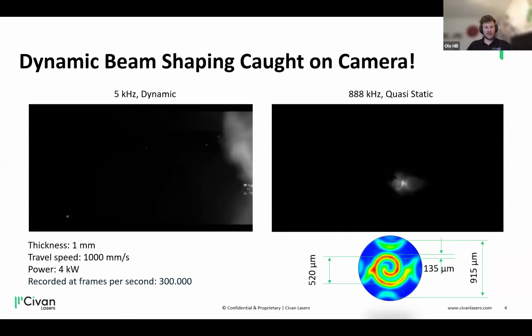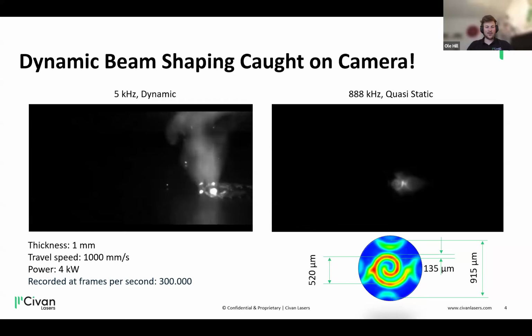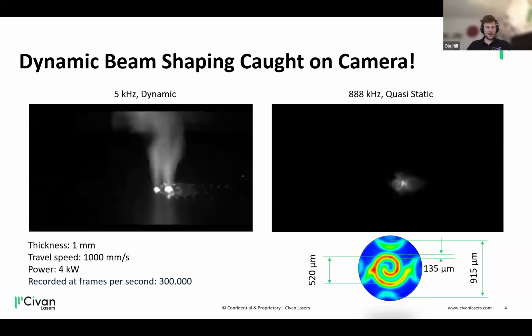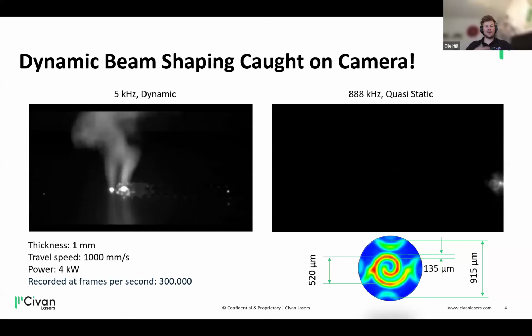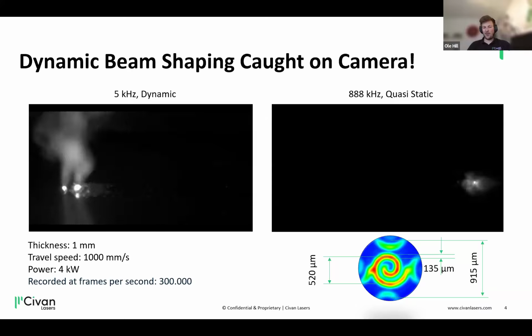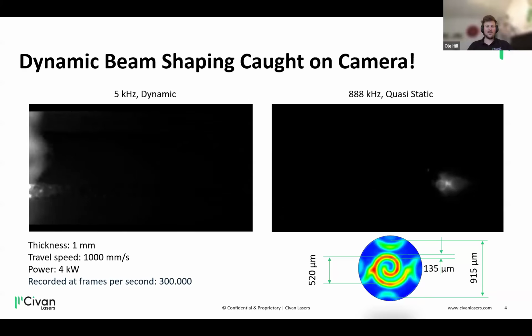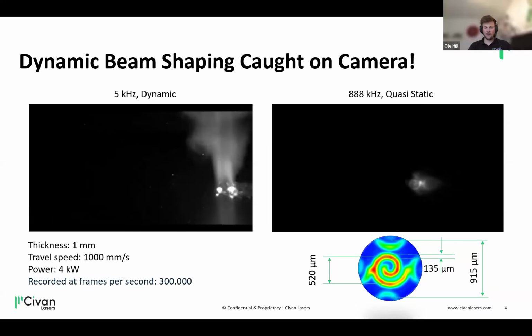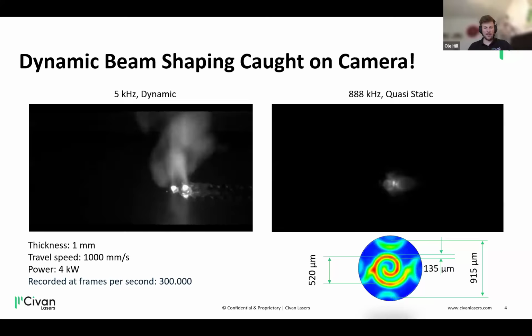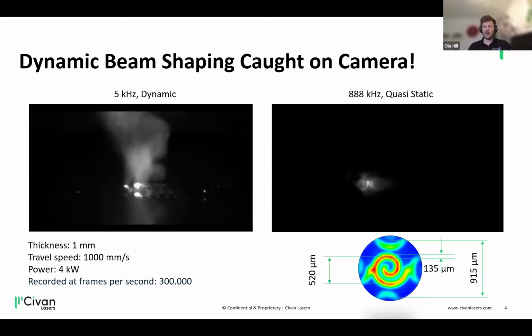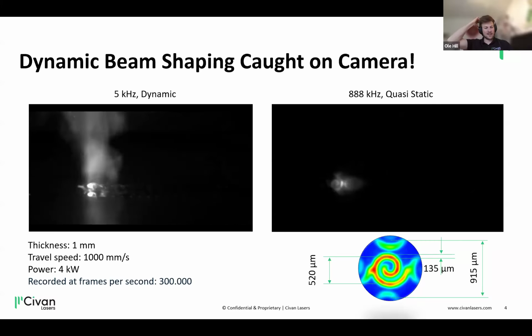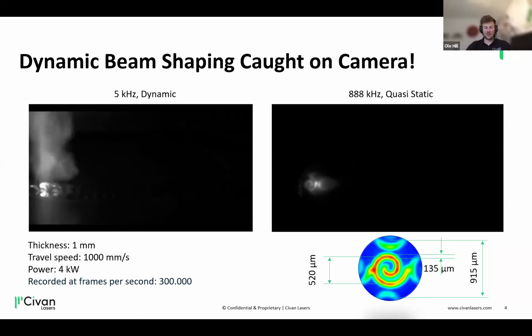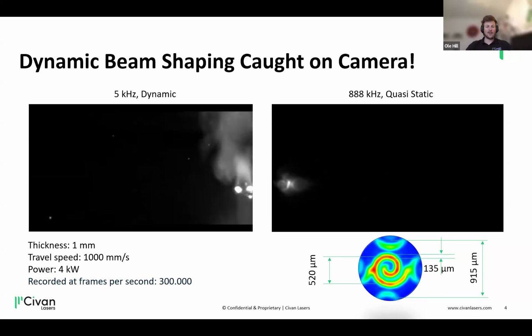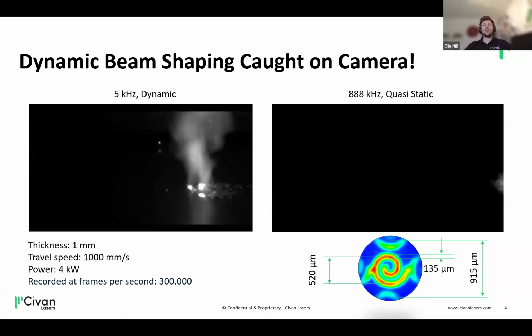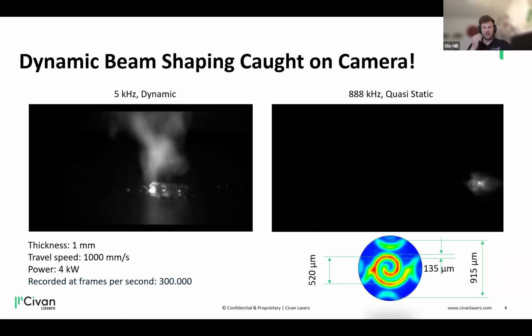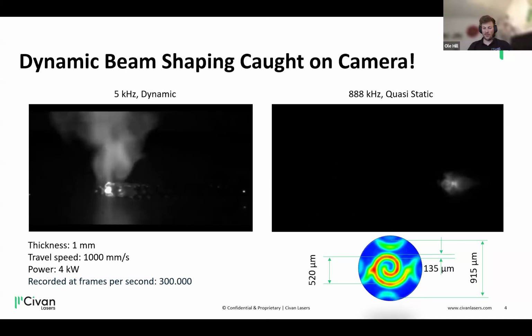And these recordings are done with 300,000 frames per second, and the spiral is rotating at 5 kilohertz. And what you can see when the frequency, which we can tune, is dialed up all the way to 800 or almost 1 megahertz, you can see a static spiral being projected onto the workpiece. It is the same beam shape, the same material, the same laser parameters, just the frequency is in a way different regime. On the left side, it's like a very fast wobble, which you could not achieve with scanner mirrors at 5 kilohertz. And on the right, it is like, maybe you know from some other manufacturers, a static beam shape, which you do with a special mirror, for example.